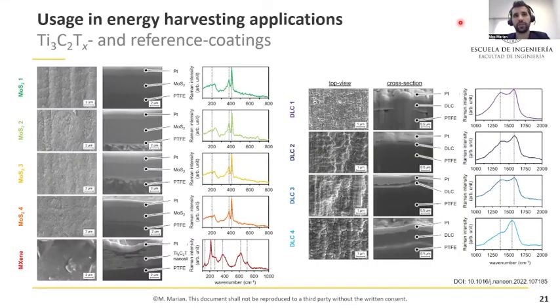So in a recent study, we deposited various wear protecting doped and undoped diamond-like carbon coatings, some MoS2 coatings, as well as a MXene film, which was also titanium carbide based. We deposited these on the PTFE surface of TENGs, which is rather prone to wear in this application and also limiting the durability of TENGs. I won't go into too much detail about all the coatings and what we did, but